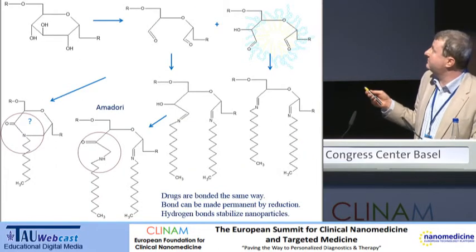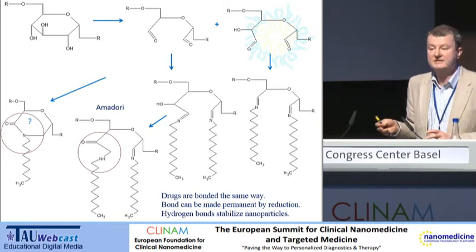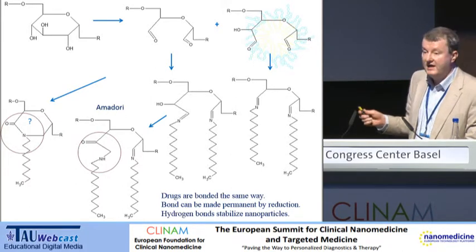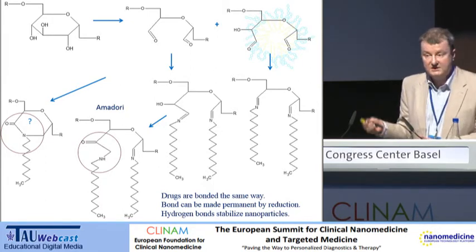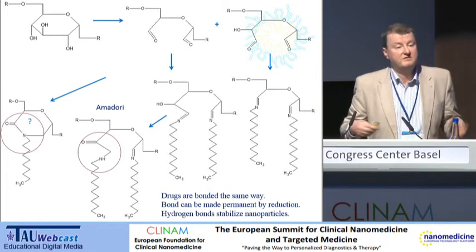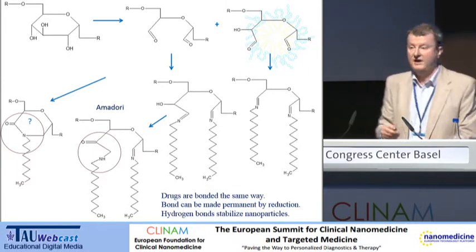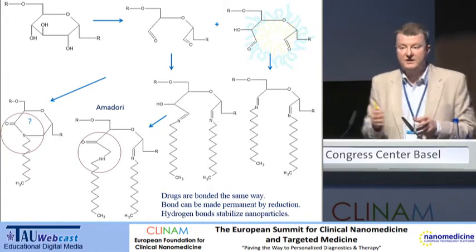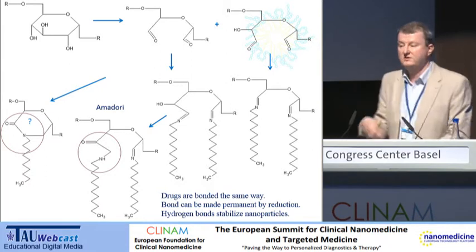It is a series of very complex chemical reactions. We even observed the Amadori rearrangement, which is probably responsible for very high stability — we think this rearrangement can happen not only within one glucose ring, but even between two neighboring rings. Those nanoparticles are surprisingly stable. We tend to have a Schiff base bonding, which is very easily and quickly hydrolyzable in water. This Schiff base we can easily reduce using sodium borohydride, which is very nice because we can make this bond unhydrolyzable and permanent. This amine bond can actually show us the fate of the nanoparticles without releasing any agent.